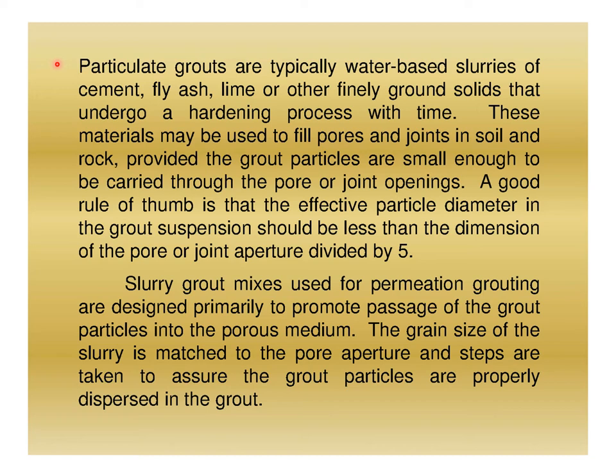Particulate grouts — the word 'particulate' means composed of different particles — are typically water-based slurries of cement, fly ash, lime, or other finely ground solids that undergo a hardening process with time. These materials may be used to fill pores and joints in soil and rock, provided the grout particles are small enough to be carried through the pore or joint opening. A good rule of thumb is that the effective particle diameter in the grout suspension should be less than the pore or joint aperture divided by five.